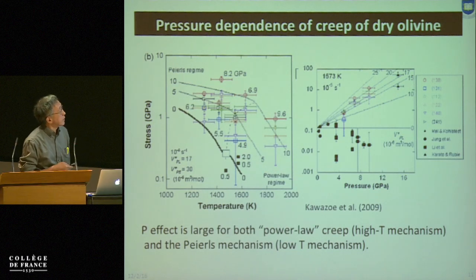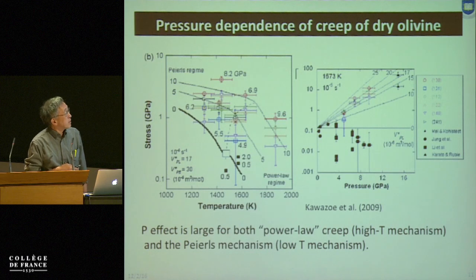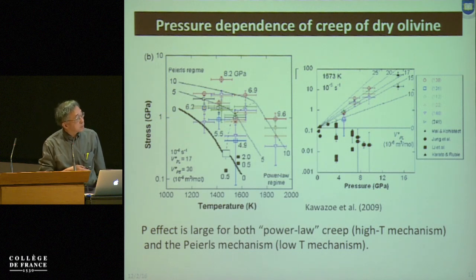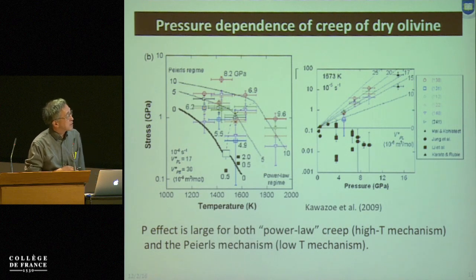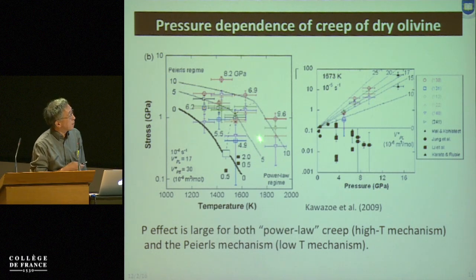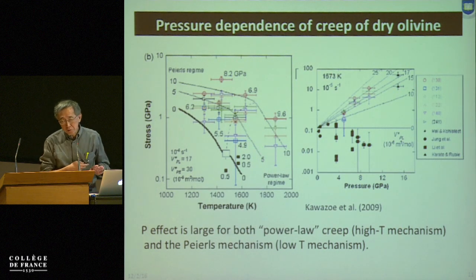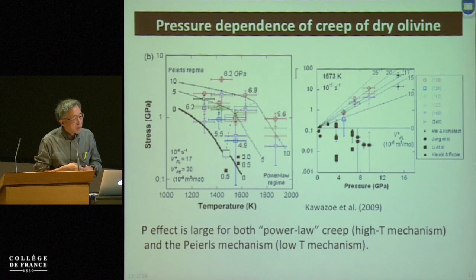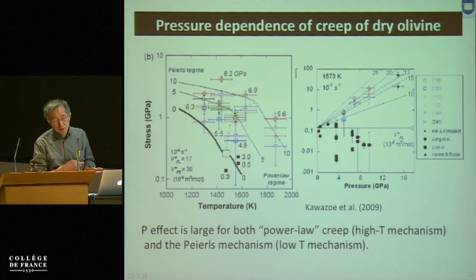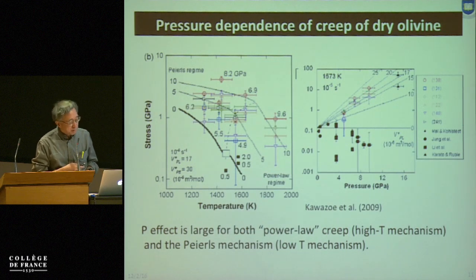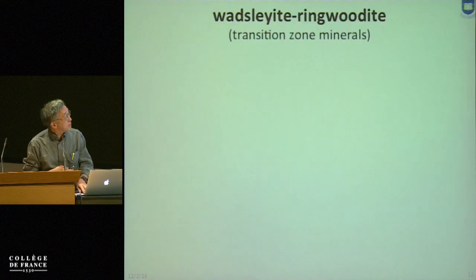For the first results on olivine, we simply deformed an olivine aggregate at various pressures and temperatures and then determined the pressure effects. Briefly, the pressure effects are very large. If you fit our results as a function of pressure, the activation volume turns out to be around 15 to 20 cubic centimeters per mole. So the bottom line is that the pressure effects are very large, both in the power law dislocation creep regime, which is a high temperature deformation mechanism, as well as in the low temperature Peierls regime. In the Peierls regime, pressure effects are also very large. So those are the findings we got from those experiments.